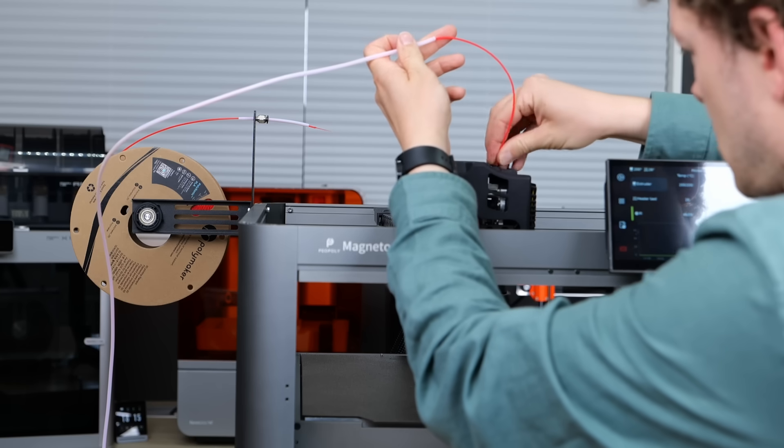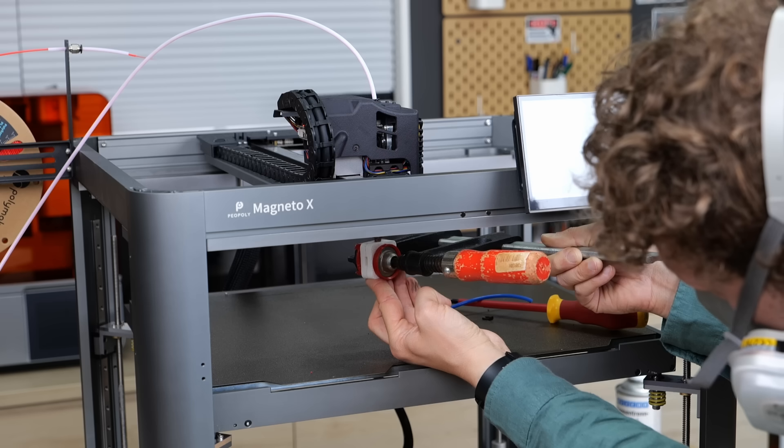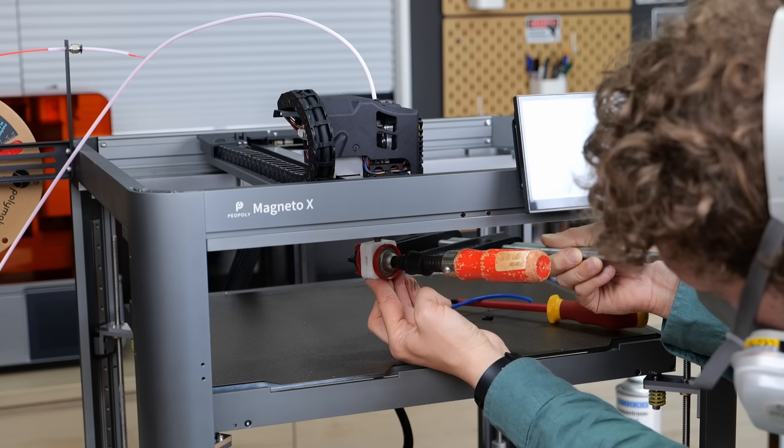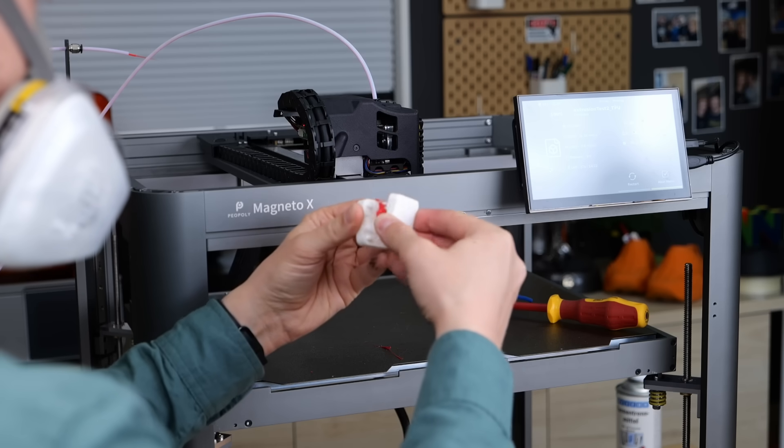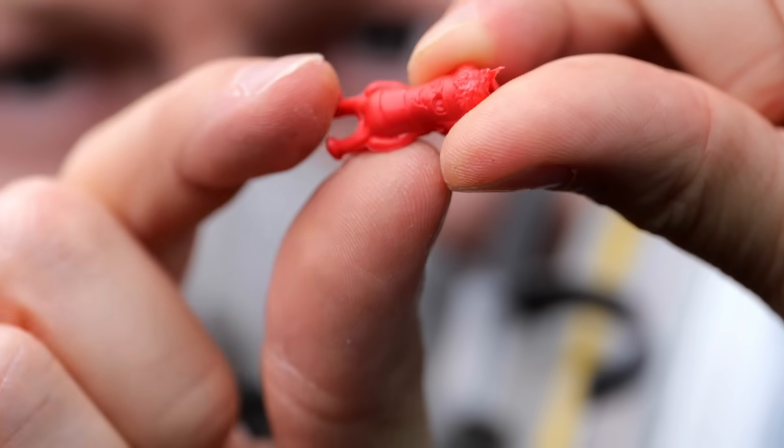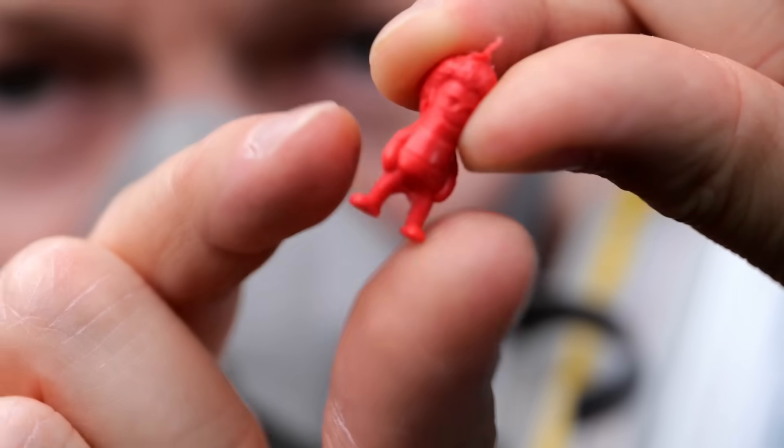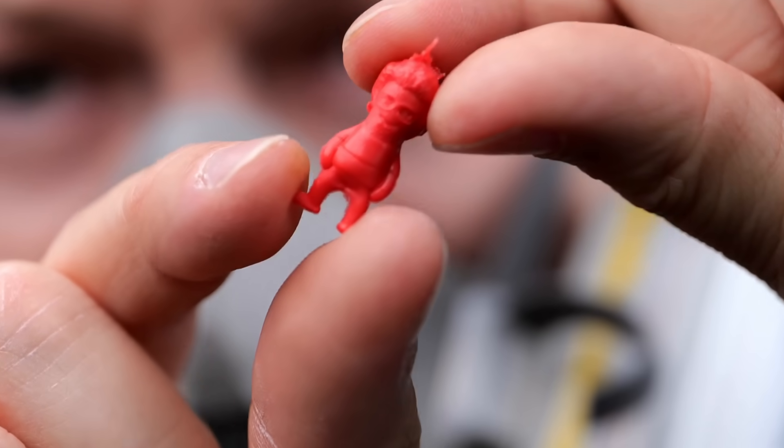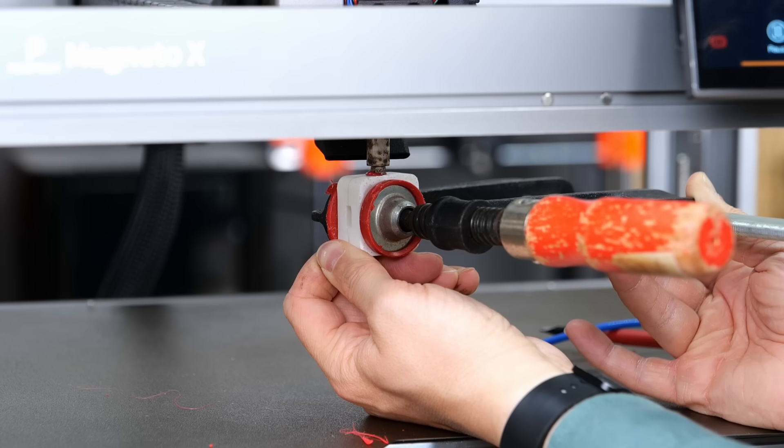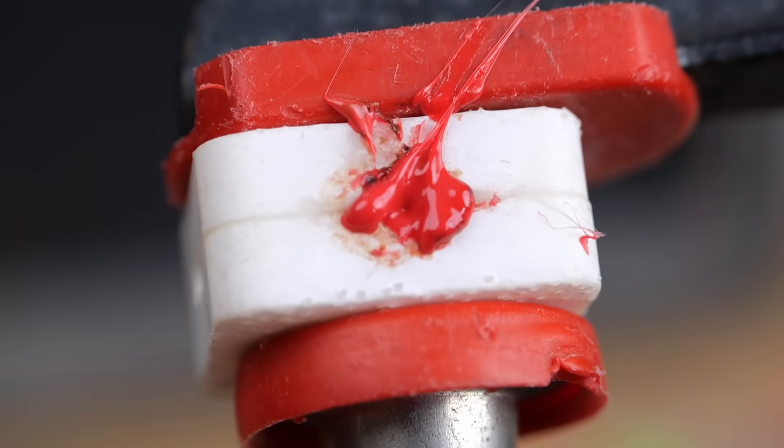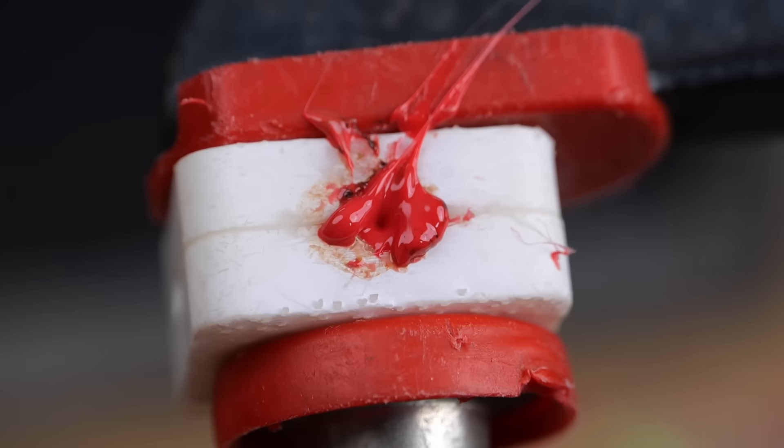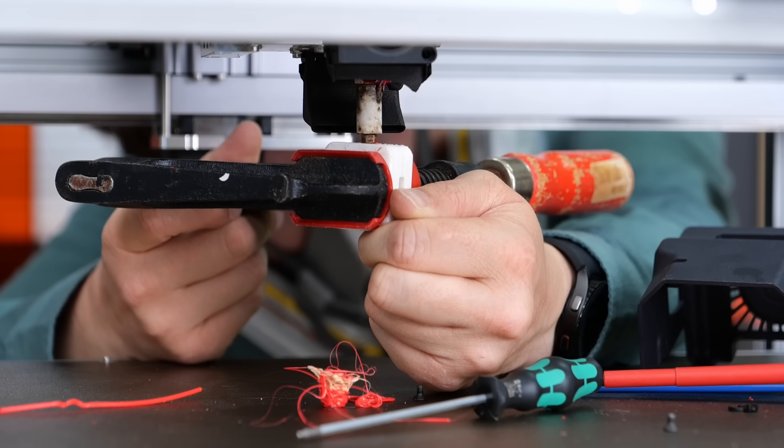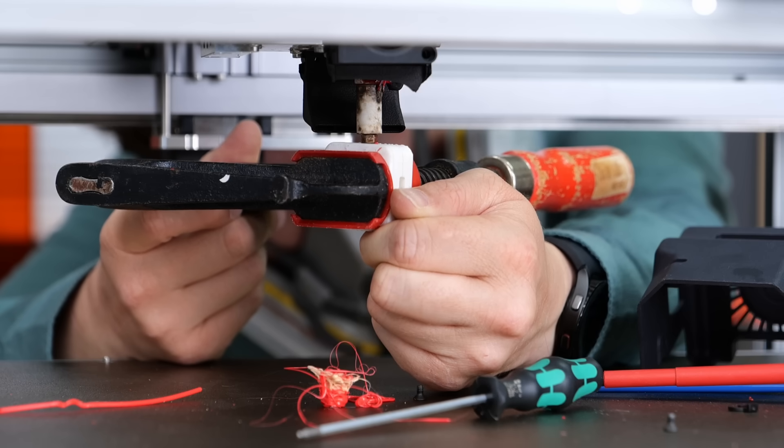Even though flexibles can usually not be extruded as fast, the Magneto handled it really well and produced a perfect Mini Stefan on the first shot. I was honestly really impressed about the details I was able to reproduce. Also, the next parts went flawlessly and it was really interesting to see how the material contracted when it cooled down, sucking a hole into the sprue. Also, my hook, which was really hard to make in PLA, turned out perfectly in TPU.